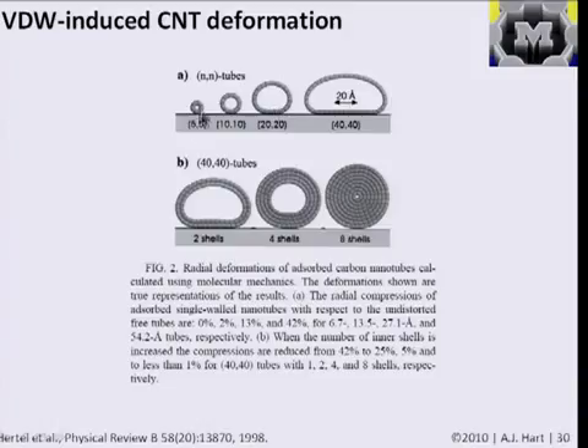realize that because of the pulling or the attraction between a flat substrate, and I don't remember what this substrate is, this could be a silicon substrate, and the atoms in the nanotube, these are for single-walled nanotubes, so here the diameter is getting bigger, so it's becoming, you could say, easier to squash. You can see that because the surface pulls on the atoms all through the tube and pulls down at the sides and then actually can feel the atoms up above, you actually result in a non-negligible deformation of the tube itself. So if this is a perfectly flat surface, this is actually what happens.